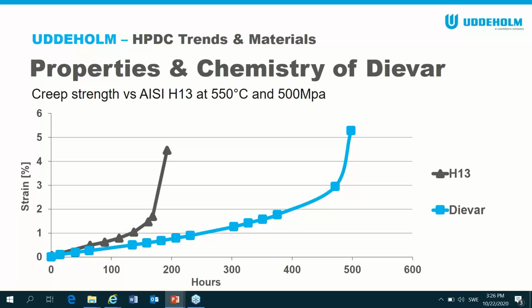So in H13, it starts to go around about 150 hours. You can see there the curve. And in Dievar, the same level is about 250. And actually, it doesn't really start to move until about 400 hours. So it's a significant difference against H13.